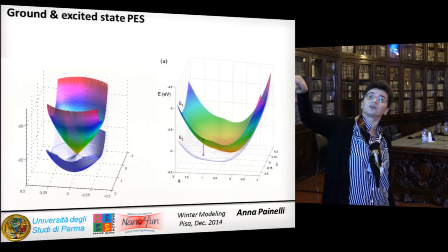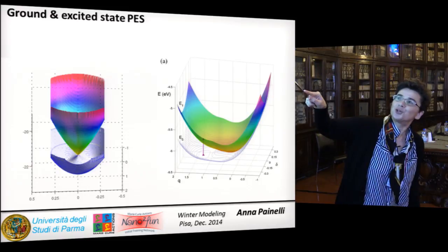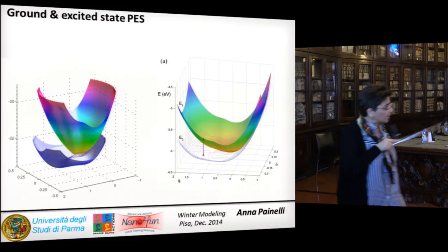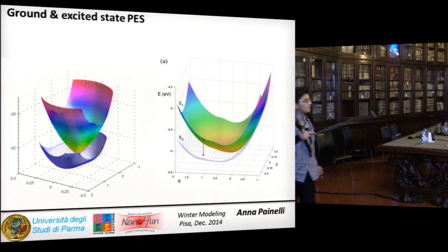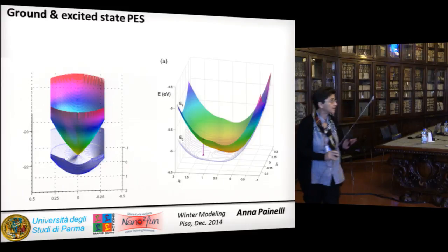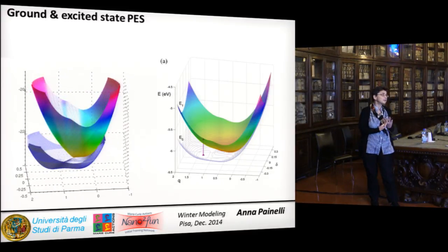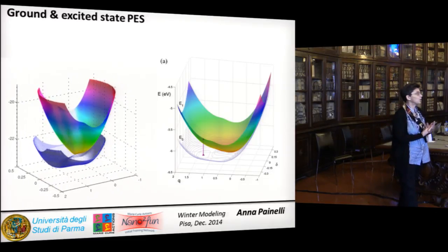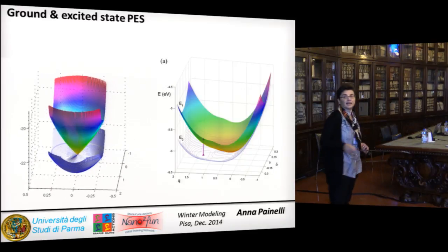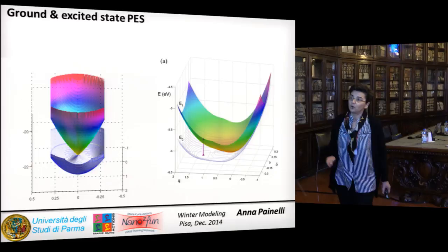This is the same picture. It rotates, again to show you how clever I am, no, to show you that there is what you call a conical intersection. But this is very peculiar because this happens in the ground state. So this is the lowest potential energy surface. This is not an excited state. This is the ground state. You have this sort of intersection basically because you have a discontinuous phase transition where several diabatic states cross, and then you have this sort of intersection here.